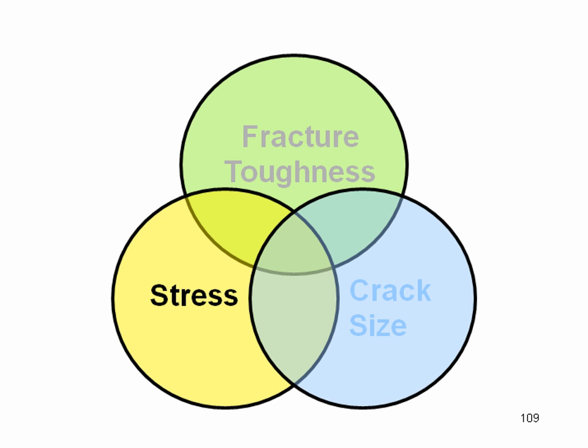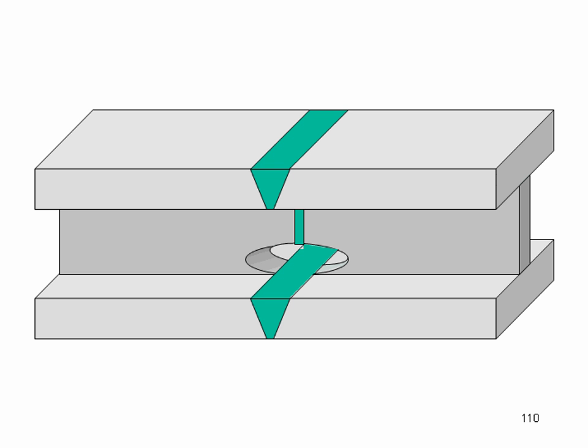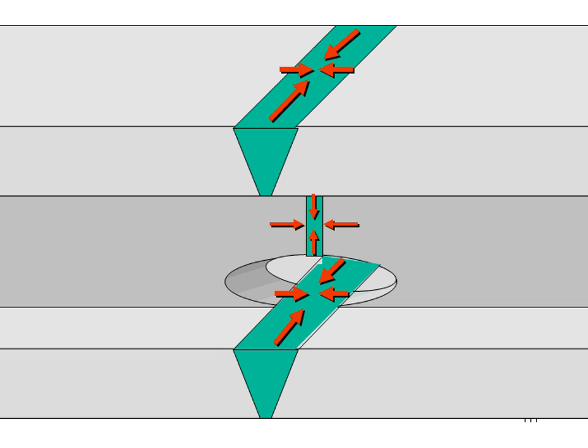Well, here we have a CJP groove welded splice of one of these heavy sections. Now, of course, we provide the weld access hole that allows us to put backing underneath that top weld. It allows access for welding through the full width of that flange. But it turns out weld access holes do more than just that. I'd like you to think about the shrinkage that those groove welds make. This groove weld, the groove weld down below, will shrink transversely. It shrinks longitudinally. The web weld shrinks transversely.